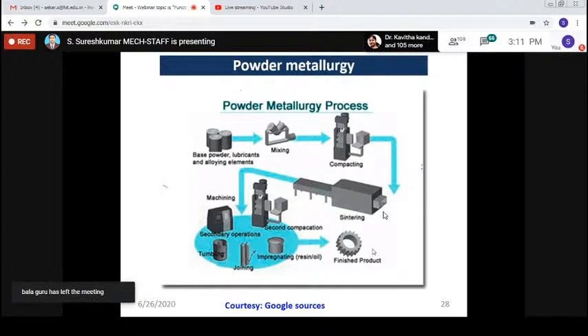It is a very conventional way, but for functionally graded metal matrix composites, the material that you are adding to the die will vary. In the first phase, you can add a mixture having a particular ratio of reinforcement. In the next stage, you can have more reinforcement, a mixture having a higher percentage of reinforcement. The third level may have an even higher reinforcement percentage. So thereby you can make a stacking arrangement of the mixtures. Finally you will end up with a material having different reinforcement content.